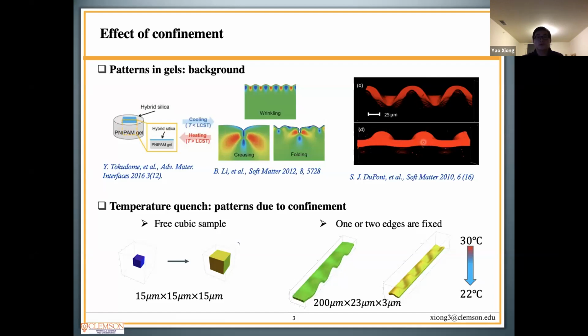by clamping the edge of the membrane. For thermal-responsive hydrogels, varying the temperature could result in a change in their volumes. If there is no restriction, those hydrogels can freely swell or shrink in all three directions, and we cannot achieve patterns. However, if one or two edges are clamped and the expansion is sufficient, we can observe buckling in those confined hydrogels. And in our research, we choose this type of confinement.